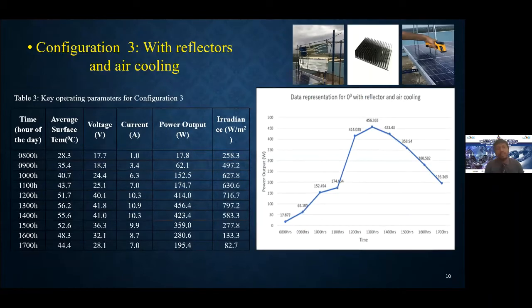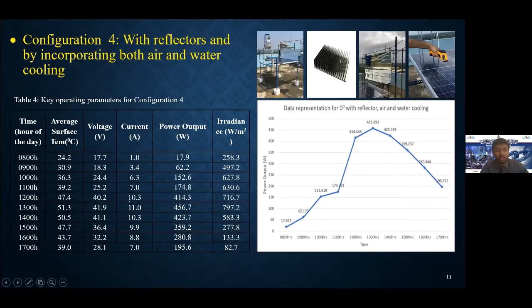And now we'll see the measured results with configuration number 3. Now this is with reflector and air cooling. Here we were able to reduce the average temperature to about 56.2 degrees Celsius, and we were able to reach a higher value of power output, which is 456. From 800 hours to 12 noon, there's an increase, but the increase is not that drastic. After 1 o'clock, when the irradiance value is lower, the power output will also gradually decrease, but there's no drastic drop. Configuration number 4, with air cooling and water cooling, we were able to reach a maximum value of 456.